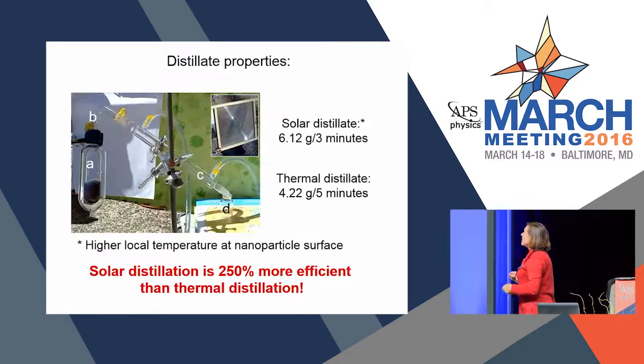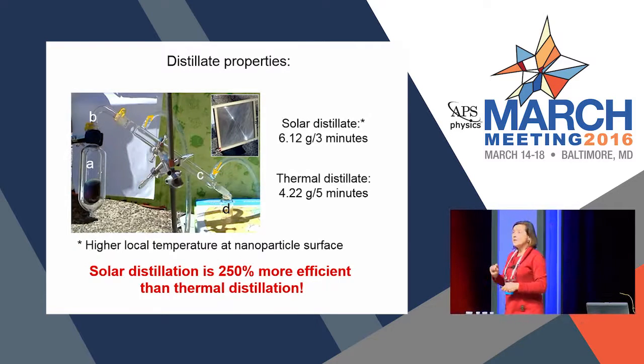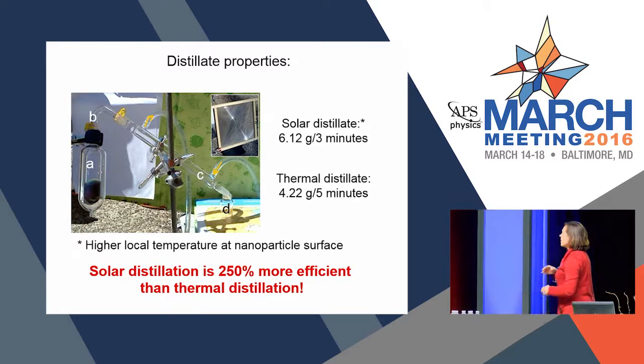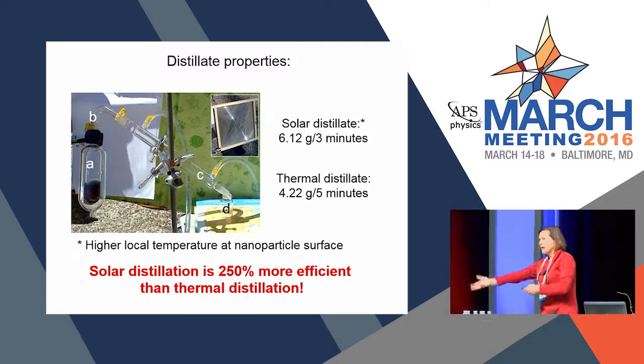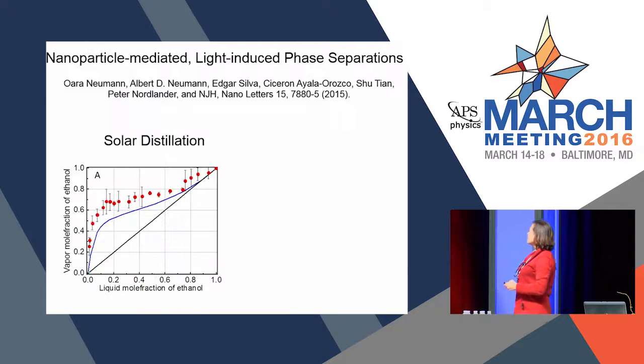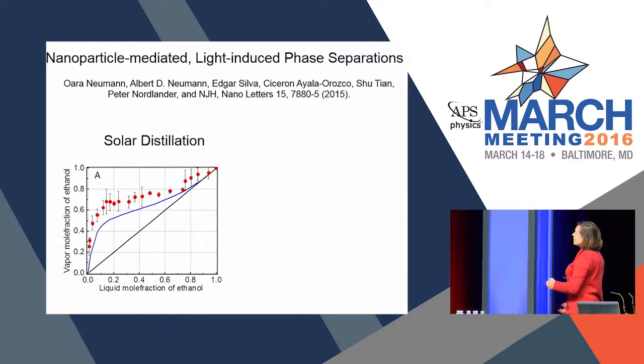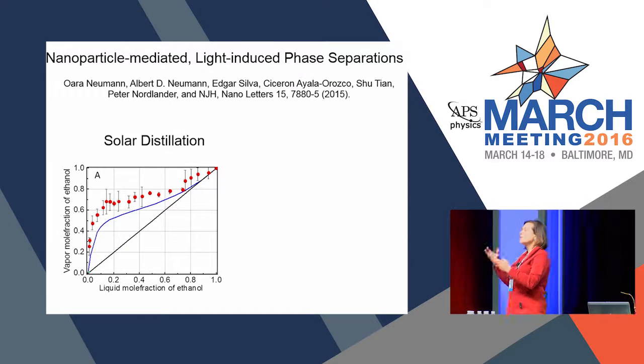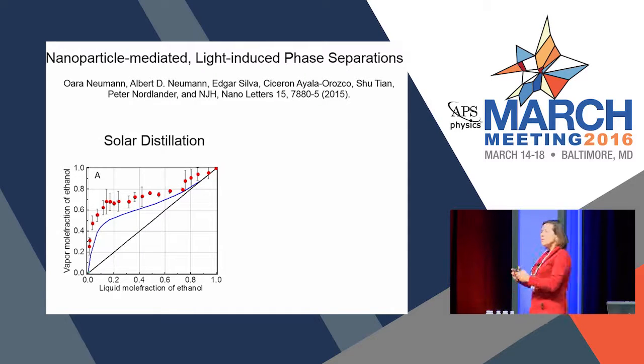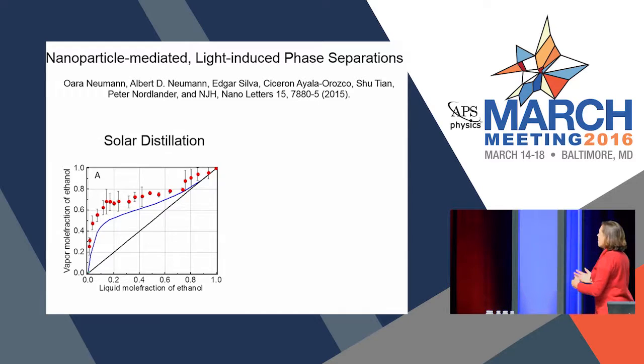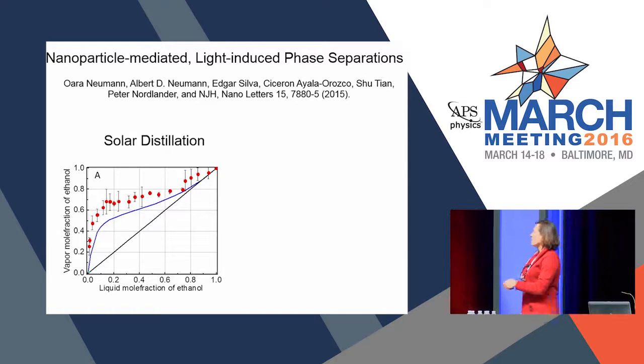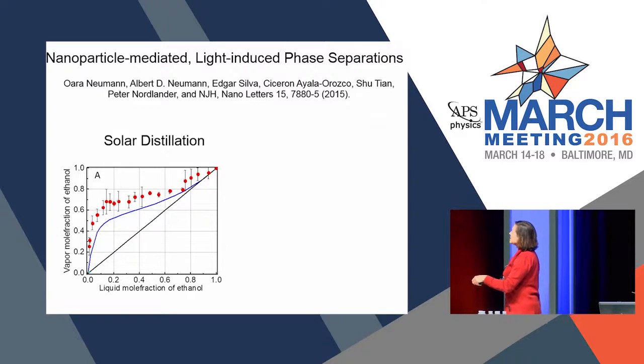So we go back outside to our solar simulator with water and ethanol, and we find that, first of all, we make a lot of ethanol right away, as opposed to the thermal process where we have to heat up our water-ethanol mixture. But when we actually look at the distillate, we find that it's much richer in ethanol than what we would normally find from our standard water-ethanol azeotrope. And those of you who remember your chemistry books or your physical chemistry book saw this water-ethanol distillation curve.